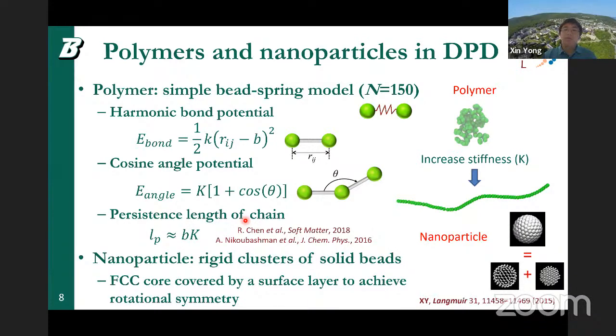Now, in order to model nanoparticles, we simply introduce them as rigid clusters of solid beads put together. The only slightly special thing we're doing for a spherical nanoparticle is that we create these particles by superimposing a face-centered cubic lattice core, as you can see here on the right, with a surface layer where the beads are uniformly placed on a spherical surface. The reason for doing this is that we cover the core with this surface layer in order to achieve high rotational symmetry. Otherwise the core would be more like a polyhedron instead of a spherical shape.